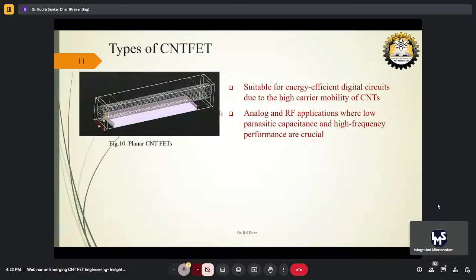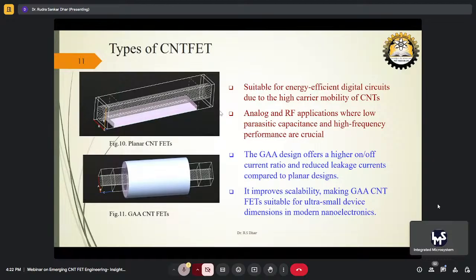This is a planar CNT, and this is a GAA, gate all around CNT. As you can see, this is the gate all around structure. The GAA design, as we know, offers a higher on and off current ratio and reduced leakage current compared to planar. So we went for the GAA option, gate all around device. Initially we developed the channel based on the CNT we want to take. In this case, we chose the 19.0 option of chirality, and therefore we took the channel region, the CNT tube, and demarcated the source and drain electrodes based on the lengths that we wanted, and thereafter added the oxide and the metals on top of the CNT.